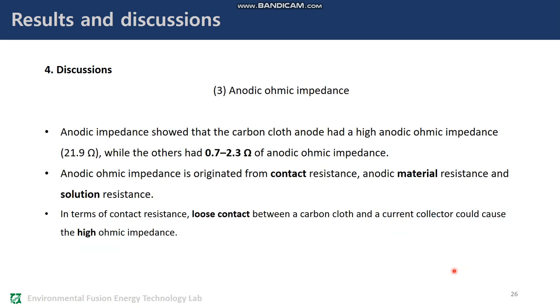Three, anodic ohmic impedance. Anodic impedance showed that the carbon cloth anode had a high anodic ohmic impedance with 21.9 ohms, while the others had 0.7 to 2.3 ohms of anodic ohmic impedance. Anodic ohmic impedance is originated from contact resistance, anodic material resistance, and solution resistance. In terms of contact resistance, loose contact between a carbon cloth and a current collector could cause the high ohmic impedance.